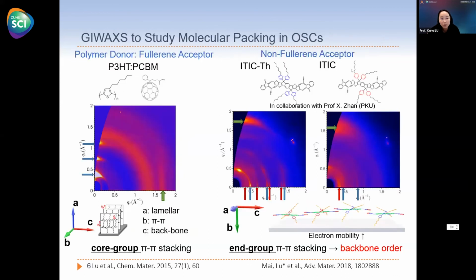Okay. So here, let me give you some examples of how we use GIWAXS to understand the molecular packing structure inside the organic solar cells. The traditional, old generation organic solar cells are made of P3HT and PCBM, and P3HT will pack into a semi-crystalline structure. When we see this GIWAXS pattern, these peaks are lamellar peaks, appearing at small q in the Qz direction. So it means that these are relatively large lattice constants in the out-of-plane direction. So lamellar direction in the out-of-plane. And then this peak appears at relatively larger Q, in the Qr direction, which corresponds to the pi-pi interaction in the in-plane direction.